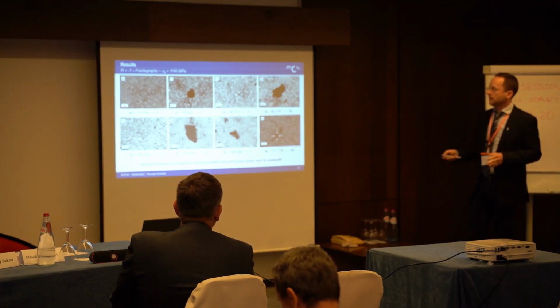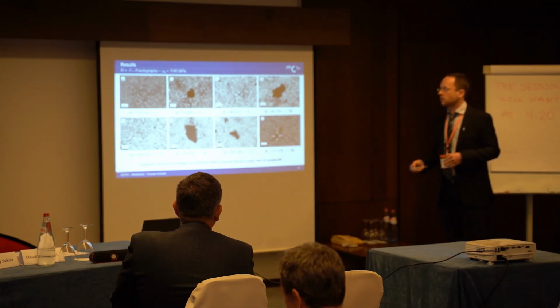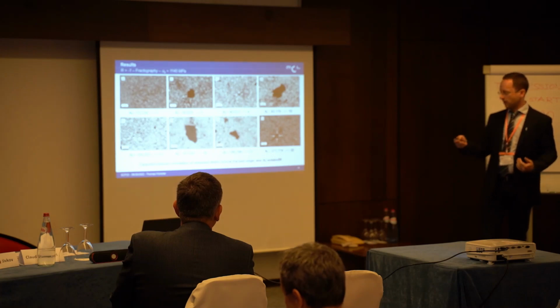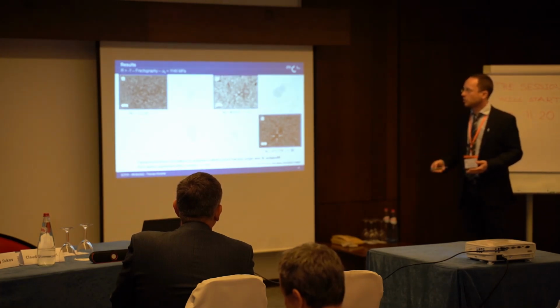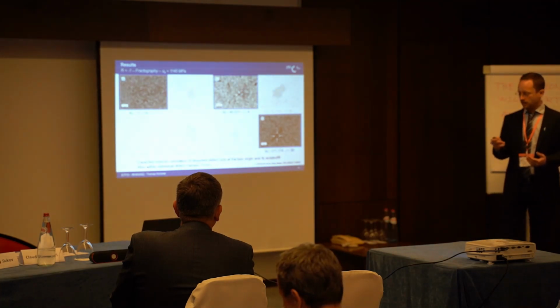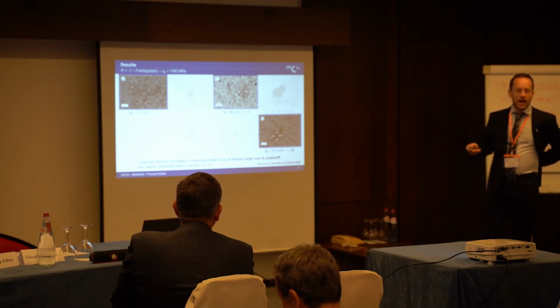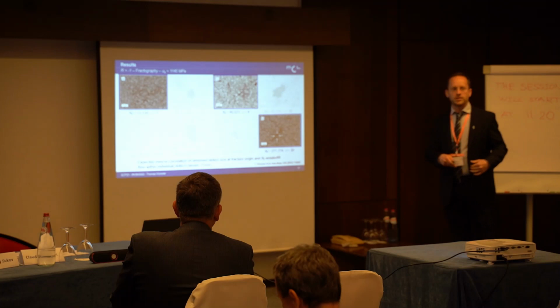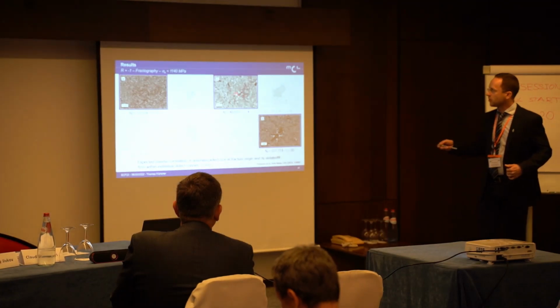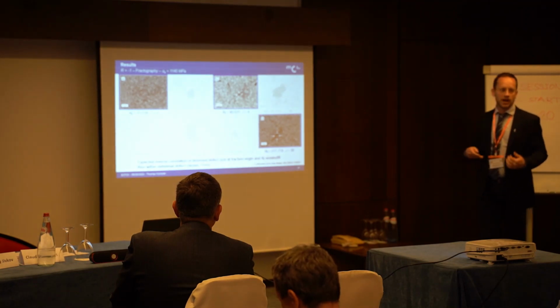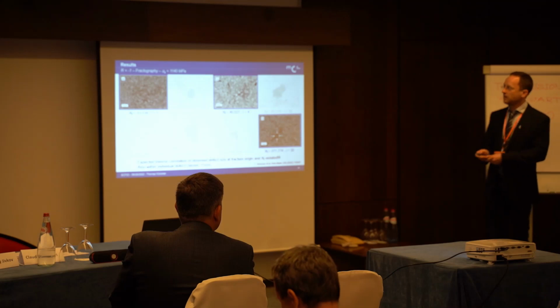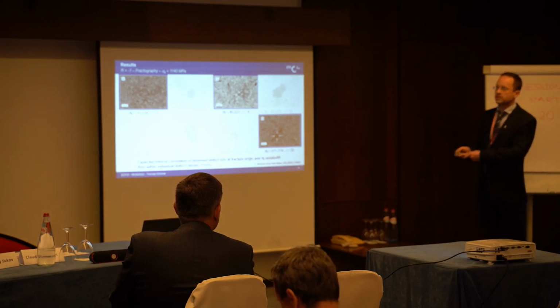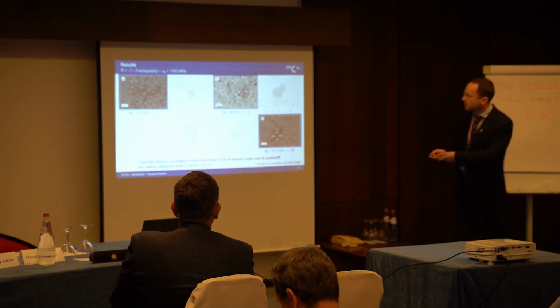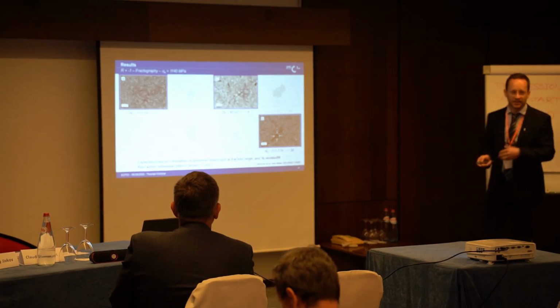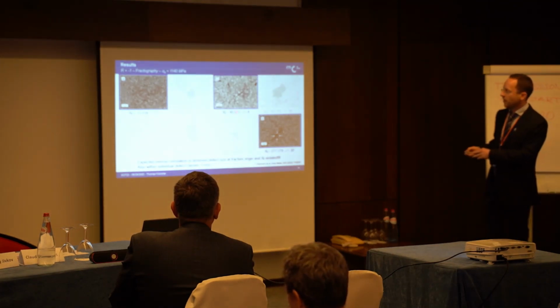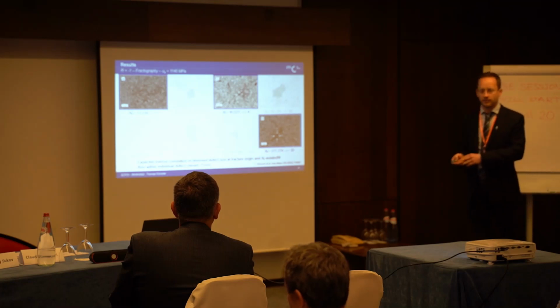What is interesting is that the ranking of the cycles to failure doesn't really correspond to what we expect to see at the origins of fracture. You see here, we have pores and non-tungsten inclusions, each an individual class of defect at the fracture origin. We see that the commonly observed ranking of, say, large defect and low NF, small defect and high NF, is not given anymore. If you compare those two here, this one here is smaller than this one. So something else has to influence the NF ranking, which is, I think, small variations in cobalt in the vicinity of those defects. You don't see so well here, but there's a lot of cobalt binder accumulation in the vicinity of this defect, which makes it fail earlier than this one here, which has an order of magnitude more NF.